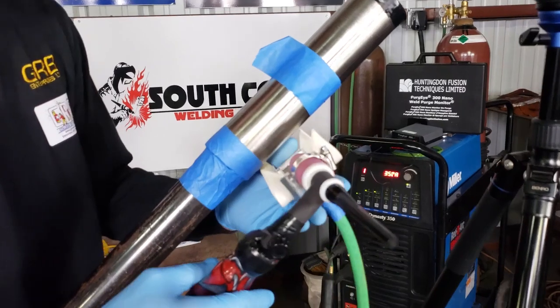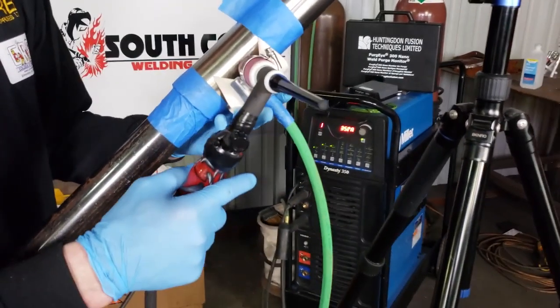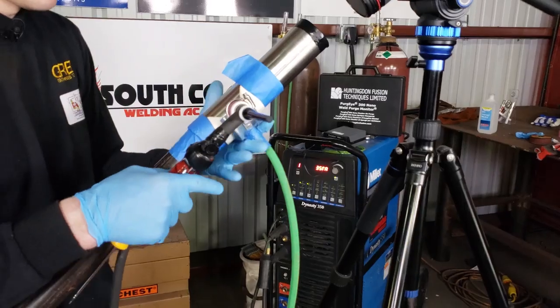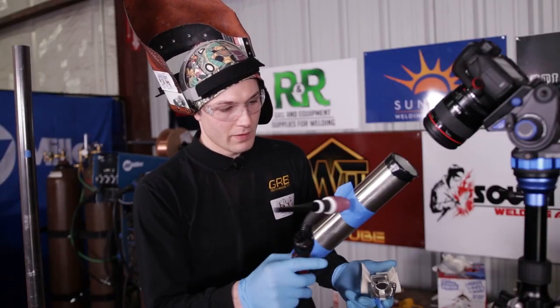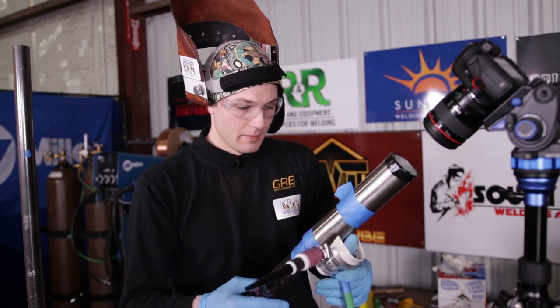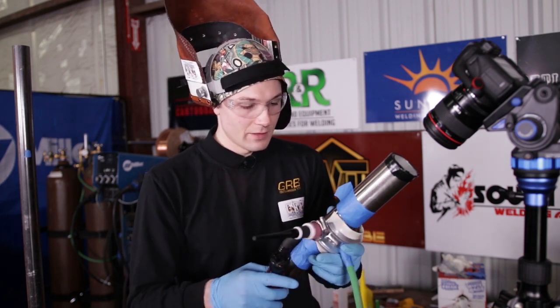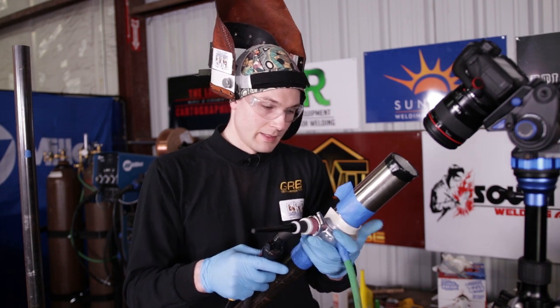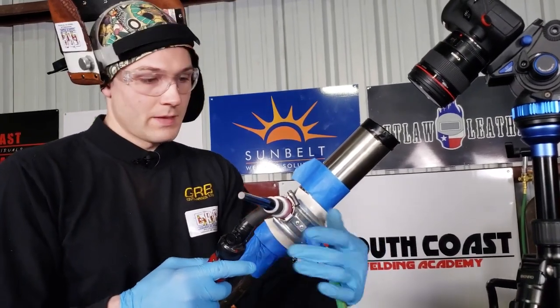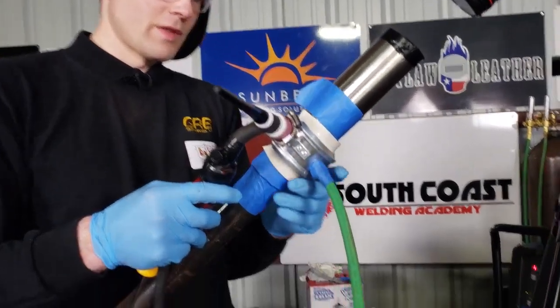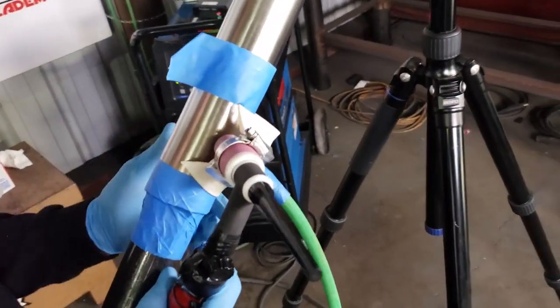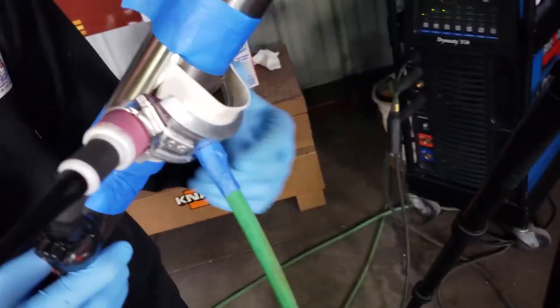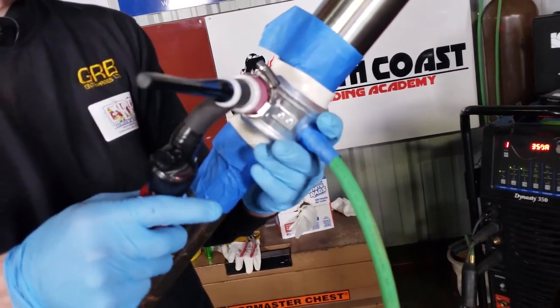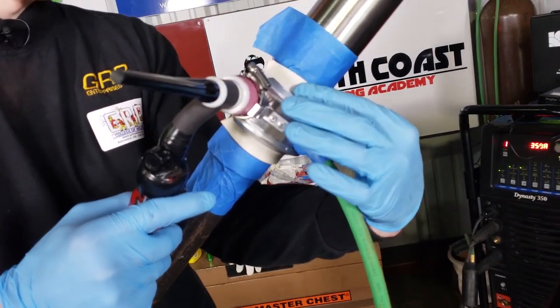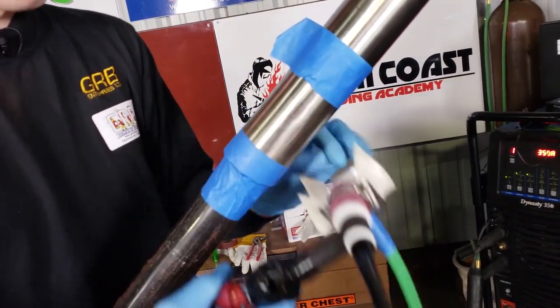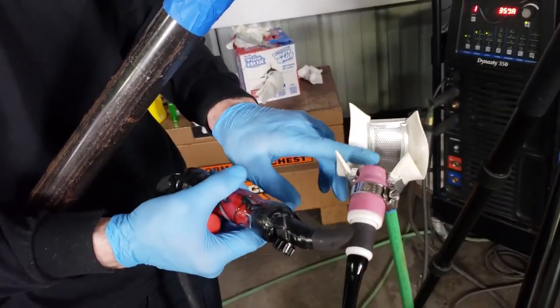Okay, essentially what I'm doing here is adjusting the trailing shield. Now titanium, you don't have to weld it with a trailing shield. You can weld it with a single ceramic cup, and every ripple that you create you protect away from the atmosphere. But since it's easier, more convenient, and you can produce a higher quality weld with a trailing shield on, I'm using a trailing shield. Therefore I'm adjusting it so that I don't have the trailing shield offset, where it lets a lot of air and atmosphere in. I want the trailing shield hugging the pipe, with a nice atmosphere enclosed within here, because this is backing gas internally in here.